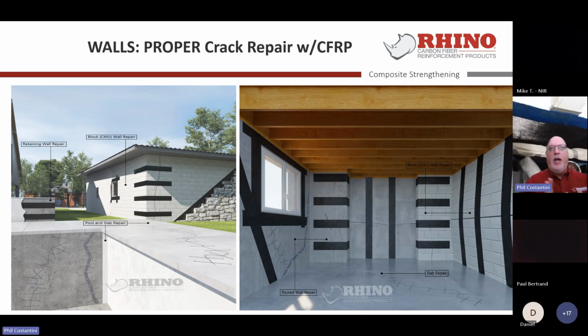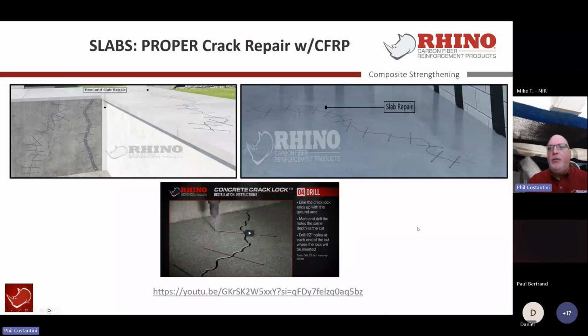Okay, perfect. So it's not going to be just good enough to do that. In this case, you can see in the slab, we're filling the slab crack with the structural saturated adhesive, which is important, right? That's helping to create stiffness. The carbon fiber crack lock stitching in slabs is giving lateral displacement support so the crack won't open up anymore. On walls, Daniel, if there's a crack in that wall, if it's a diagonal crack going up the wall or horizontally, then I'm going to ask that you inject it. Sure. Okay. Perfect. Thank you. No problem. Any other questions, comments?